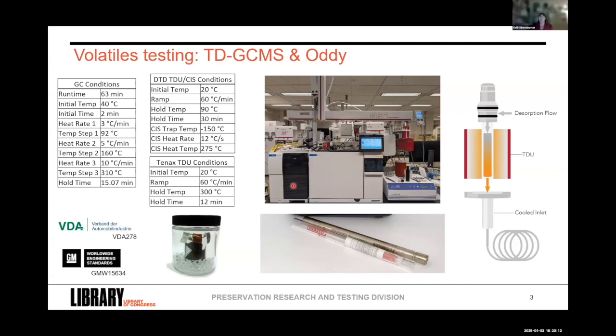We really like doing both these techniques in tandem. Sometimes the GCMS will catch things that Oddy misses and vice versa. And the GCMS, our methodology is about an hour and a half to run a sample. So it's a great early detection of what might be a problem child that we can't wait a whole month, especially with our exhibit deadlines tend to be pretty fast, and we'd get really behind if we were relying on